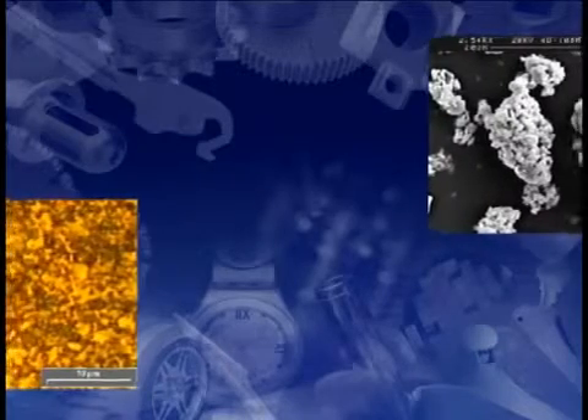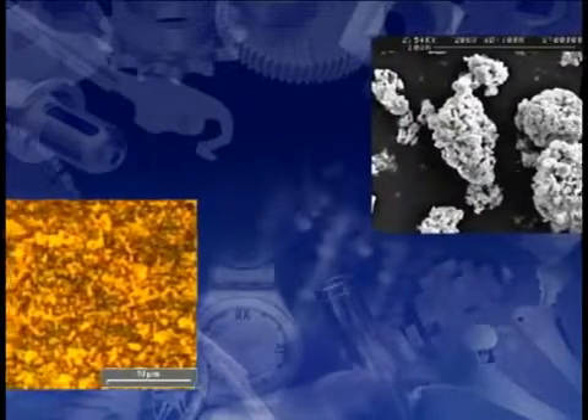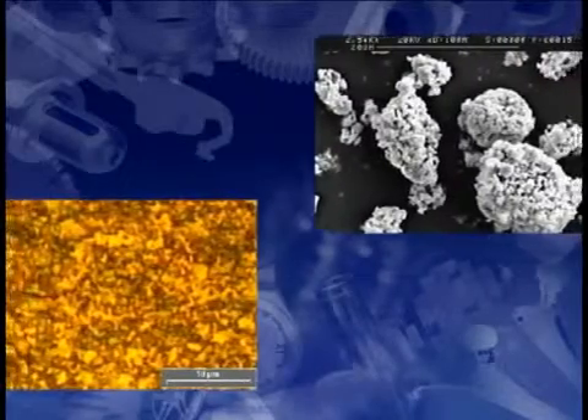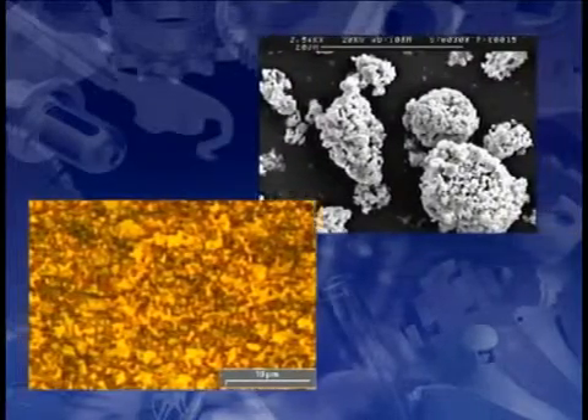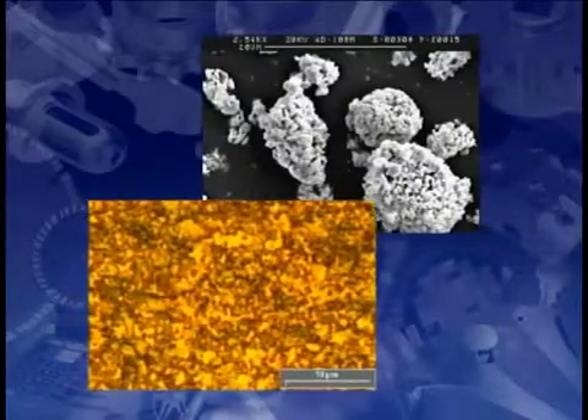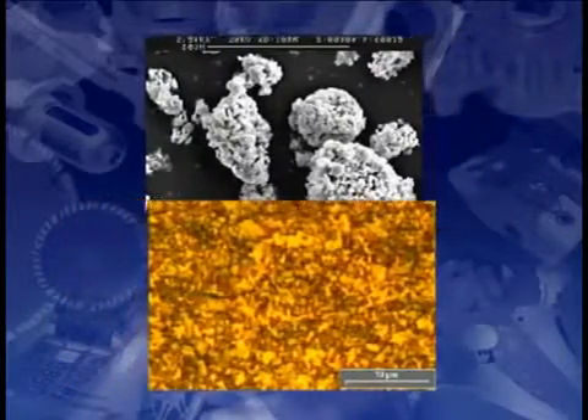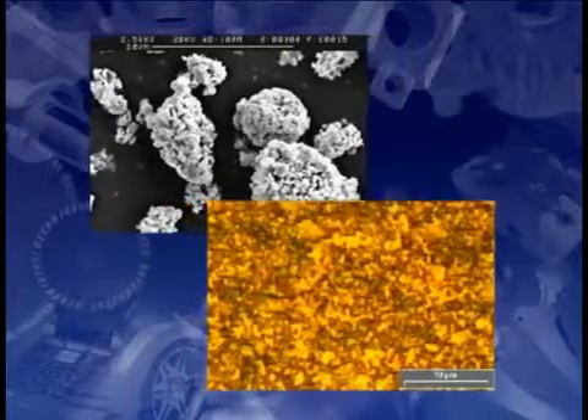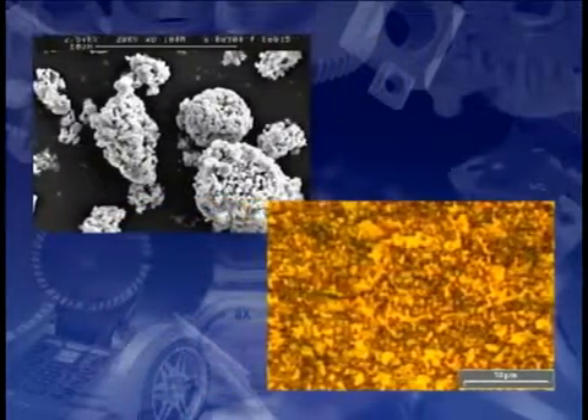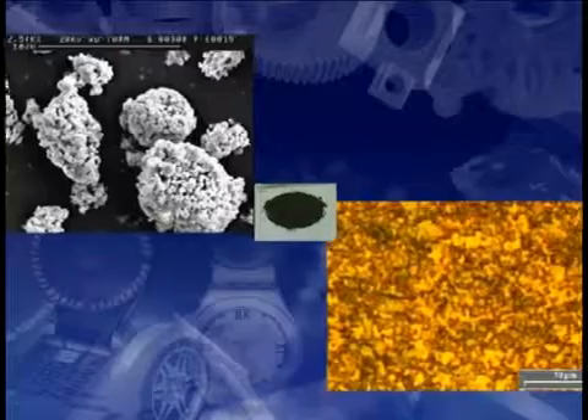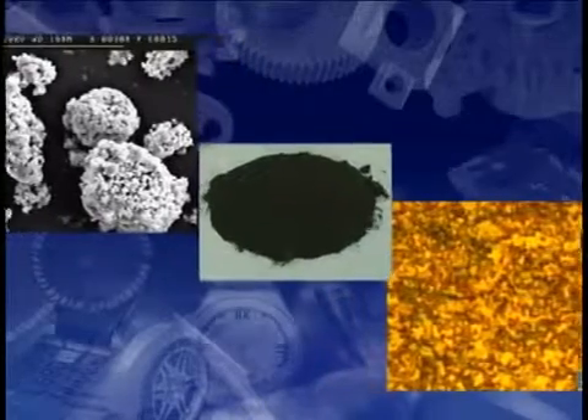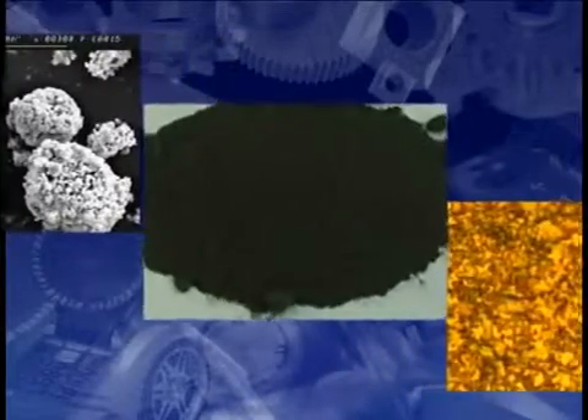Rapid cooling after sintering, faster than 100 degrees Celsius per minute, is customary in the diamond tool industry. This led to material embrittlement and posed a major challenge during the development process. This embrittlement arose firstly as a result of diffusion of tin into the iron phase during sintering, and secondly by the formation of very brittle tin iron intermetallics during the rapid cooling. Umicore found that the tungsten present in the iron phase reduced the diffusion of the tin and thus prevented embrittlement.